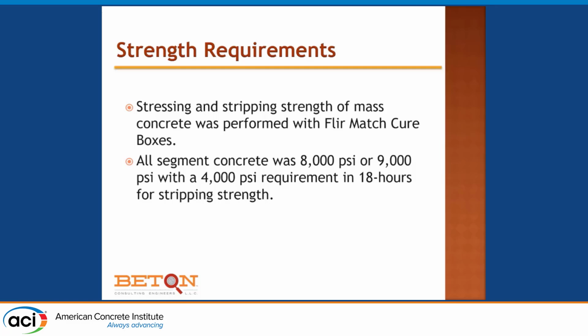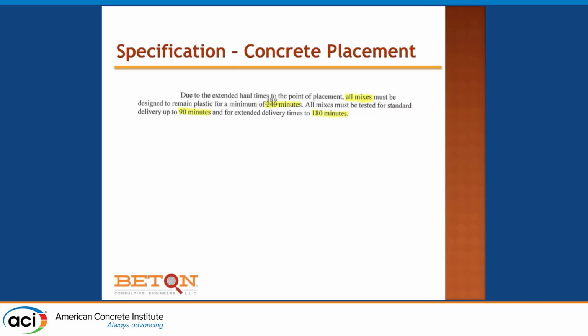So we have a bit of a problem, because the segments are being precast, and then they're being lifted in place. And those precast segments have internal transverse post-tensioning. It needs to be done very quick. There's no problem. You can use any admixtures, any supplementary materials with your binder, and you have 90 days to reach strength. But if it's not 4,000 psi in 18 hours, Rocco and Bruno over here, they're going to come visit. So I was thankfully out of the ready-mix business at this point, but we were running all of these mixes for them. Specification has a bunch of other things.